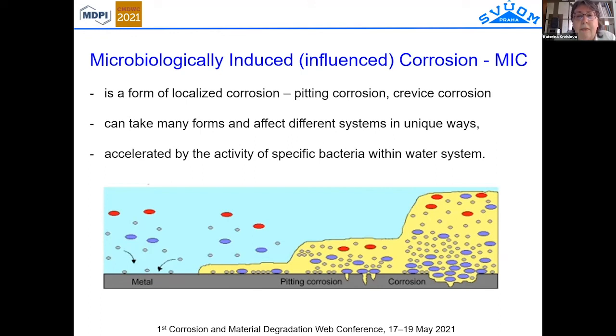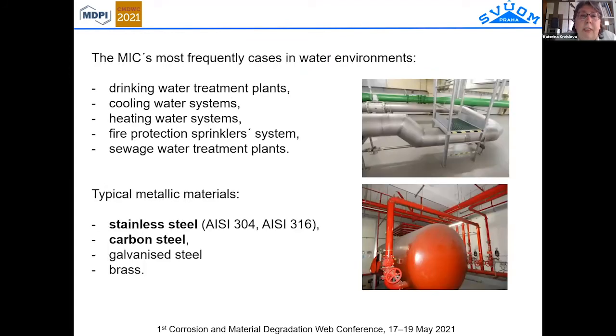We can identify pitting corrosion, crevice corrosion, and to identify if this mechanism is influenced by microbiology is very difficult, because in many cases we come to this system, to this pipeline, in cases where there is leakage, where it is penetrated, and it is problematic in a very heavily corroded surface to identify the microbiology. So what are the systems where we meet this type of corrosion?